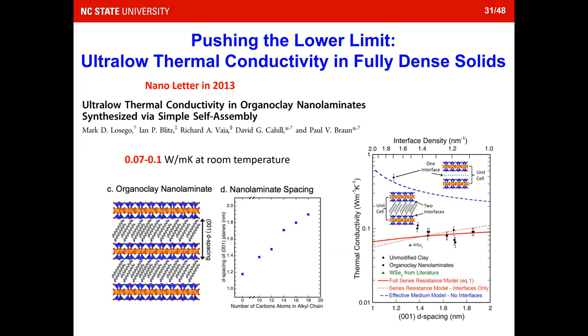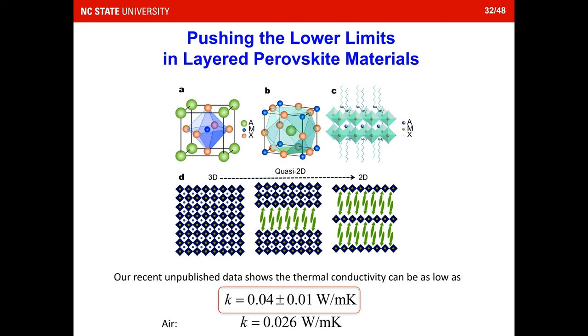It's quite already low. And then we keep thinking about, can I actually push even further to a lower limit or even beat the record established in 2007. So recently we're working on a material called a perovskite, and that is also a two-dimensional material, right? With that two-dimensional material, you have the anisotropic shape in the material, and then you can add different kinds of molecules in between. You can control the disorders in this kind of layered perovskite material. And hopefully we can achieve a very low thermal conductivity.